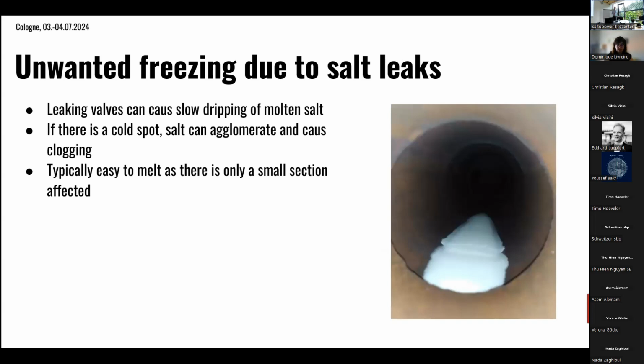Then another thing which can happen is unwanted freezing due to salt leaks. This is also happening if there are some cold spots, and we have seen that sometimes. I mean, we cannot look into the plant, so we can only assume what's going on there. But apparently, it can happen that, for example, some salt is coming through a valve. They are not typically 100% tight. And then you have the dripping, and if this continues over hours, then you might have some salt slowly dripping somewhere in the pipe, and if there's a cold spot, then it starts agglomerating and can form a clog.